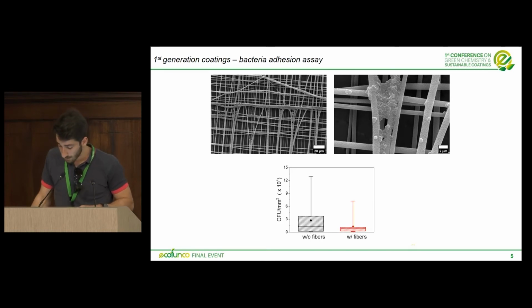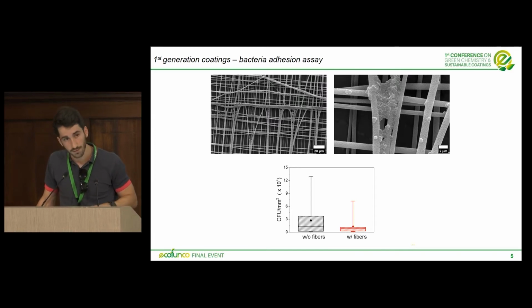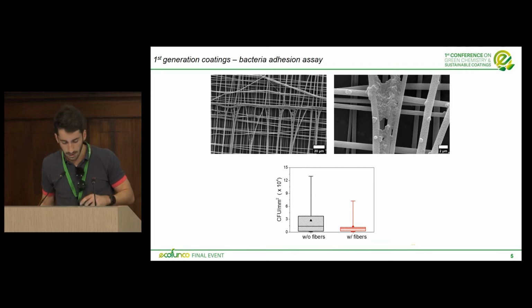And the numerical results, so considering the colony forming units per surface unit, we have found that the coating with fibers reduced the bacterial adhesion with respect to the control surfaces without the fibers, but no statistical difference was found between the surface with the coating and without the coating. So the reliability of these results was influenced by different factors. First of all, the samples were very delicate and the fibers were not properly anchored to the substrate. Furthermore, we used a type of bacteria that didn't possess dimensions of the same order of the geometrical features of the coating.